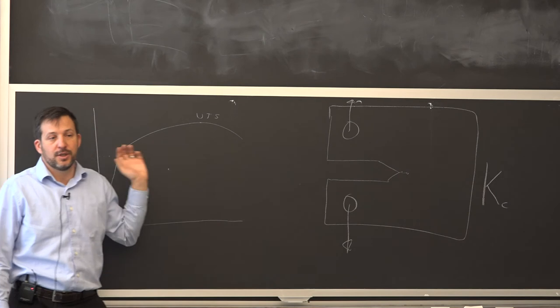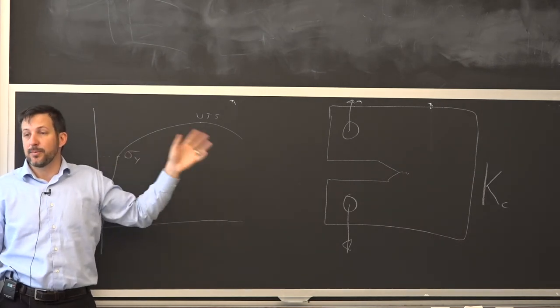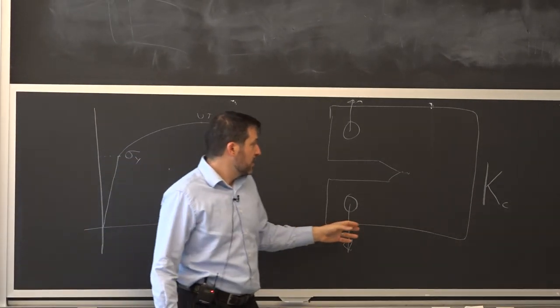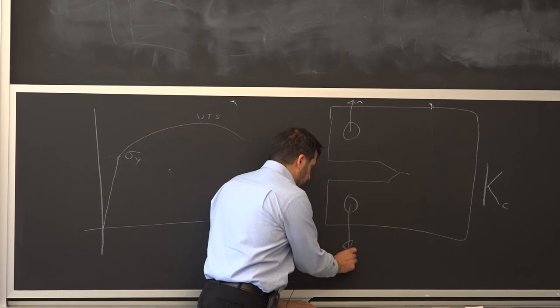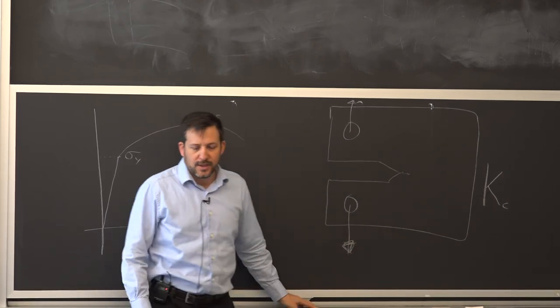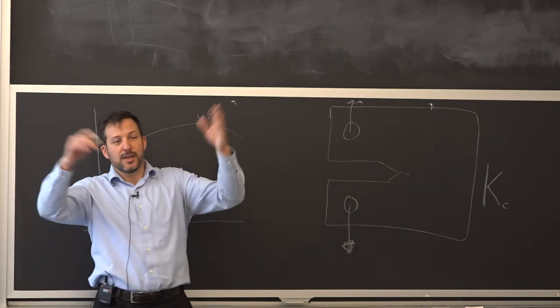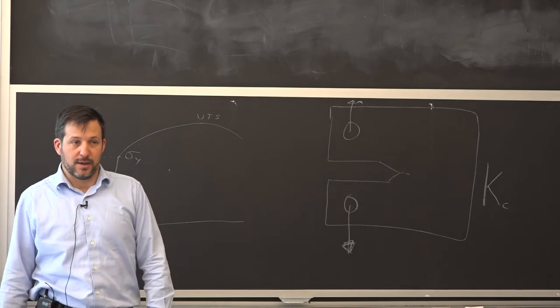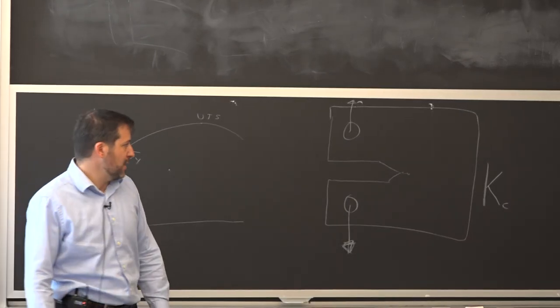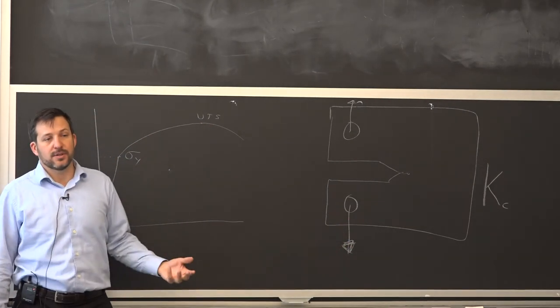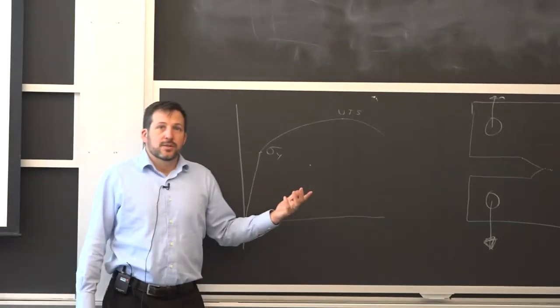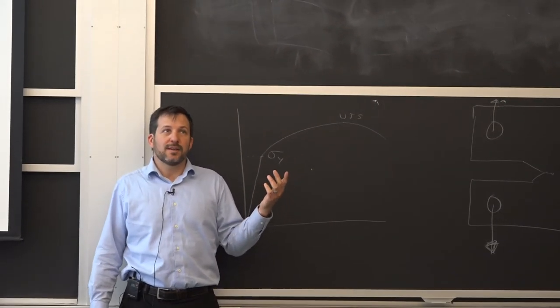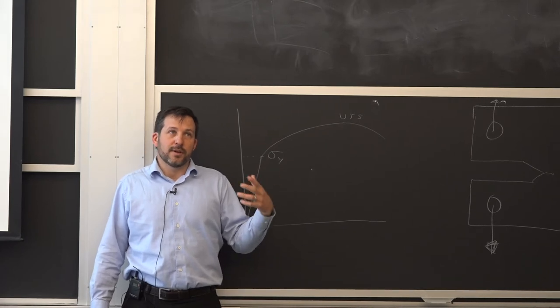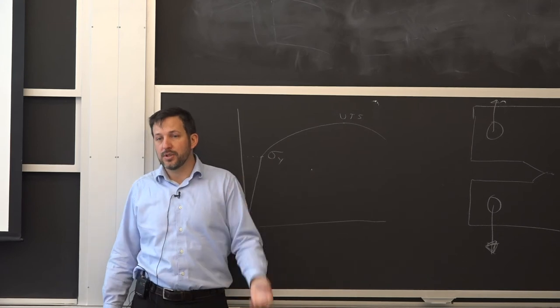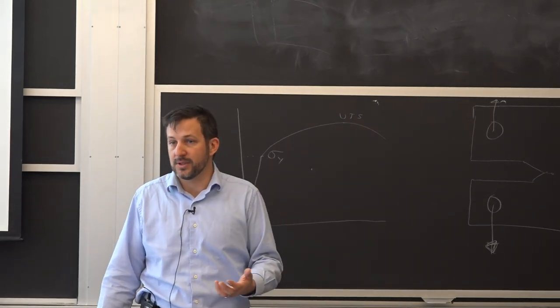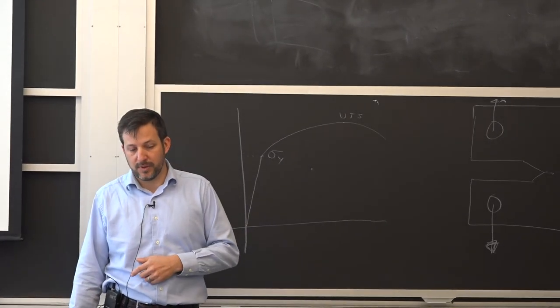Those two pieces of information are important for different applications in pipeline. The application that the customer was very, very interested in, the reason that they ask you, and you have to work this in, is if there is a crack on the pipeline and it really explodes, that's really, really bad. And therefore, they were specifically seeking out a solution for this, regardless of the details of regulation. Here, the very quick story is they were not making the news very often for something related to that. This is more for operation, to avoid small leaks, to really know what the material is, to be able to optimize your system, but it's not as related to a catastrophic failure.